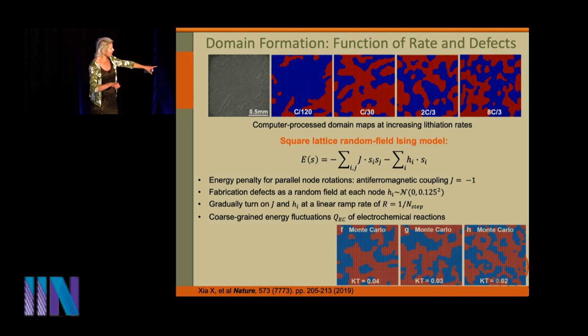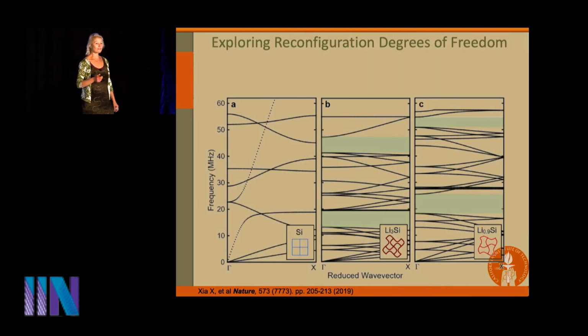So these are the simulated patterns. These are the real images and simulated patterns. And it looks like there is, in fact, quite a bit of coupling going on between the randomly distributed defects in the structures and the defects that we can program in. And so what we learned is that if you start with a silicon lattice and then you lithiate it, you form this intermetallic compound, and then you're forming this compound, your band gap, you can calculate the phononic band gap, and then that can shift based on the periodicity that emerges from the different degrees of curvature in these beams.